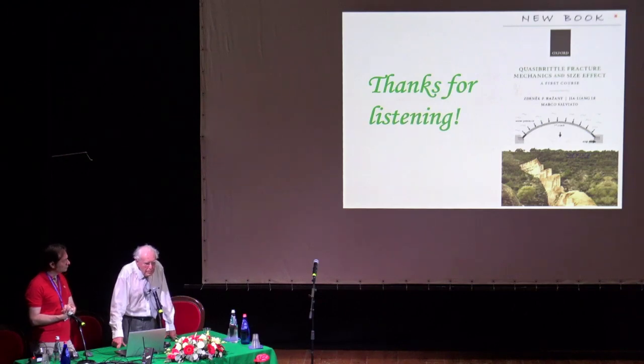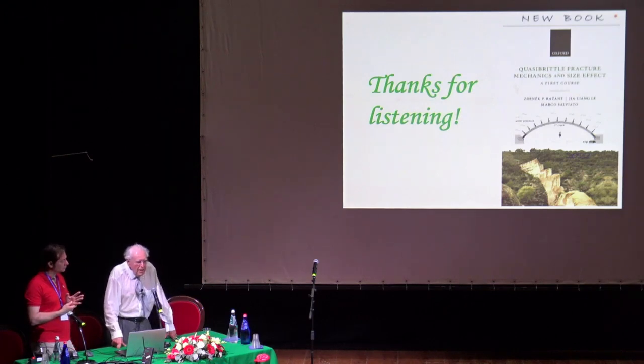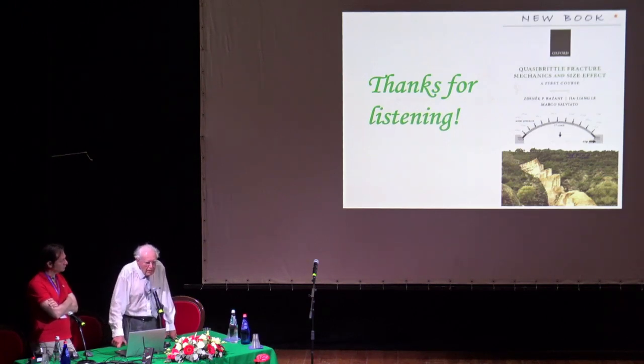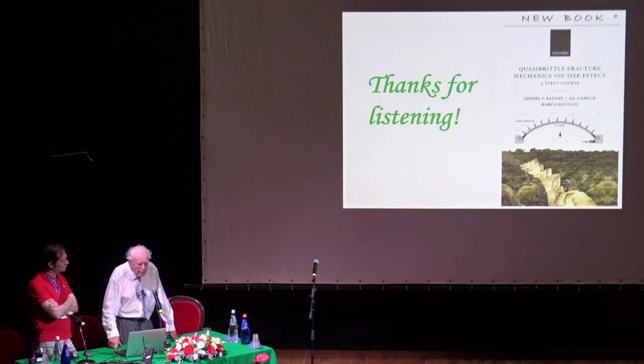And the first question on the possibility to have a relation between parallel stress and the size of the crack. Well, that's an interesting point. It might be, we have not studied that. But we are not speaking of failure in creep, unless we look at long times. Usually, structures for a long time in creep are loaded less than half the strength limit. They may go to fail eventually, as this bridge in Palau, but there was somewhat different reason.